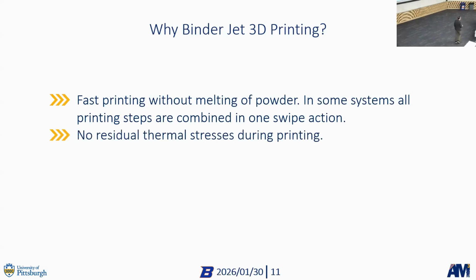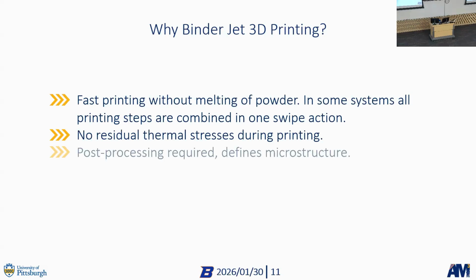We have no residual stresses during printing because there's no melting, right? So that is really, really good, especially for materials that don't weld well, right? So if you have materials that don't weld, binder jetting is really something for you. But on the other hand, you need the post-processing, right? You need sintering for densification.